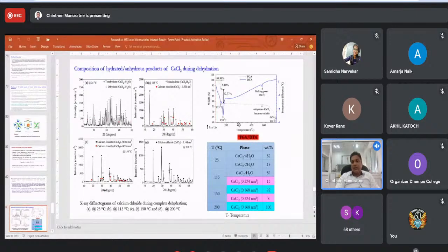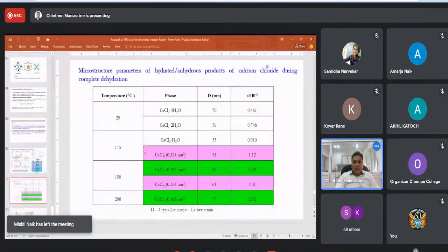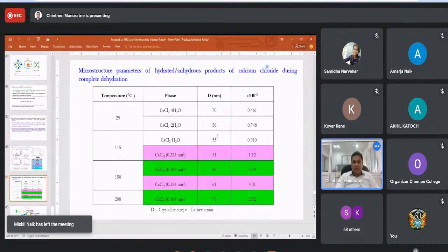And here is the thermogravimetric analysis of calcium chloride. This conversion takes place at two distinct temperatures, and above that you will have anhydrous calcium chloride. The different phases can be observed at different temperatures, with different unit cell volumes. You can see the crystallite size is also not much affected, and you can see different strain changes because of the atoms' vibration when you increase the temperature.